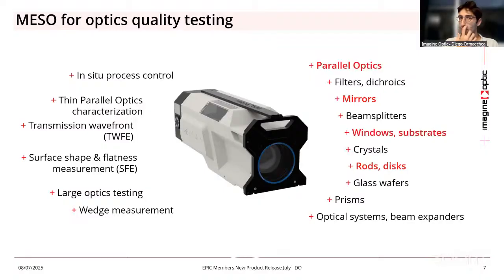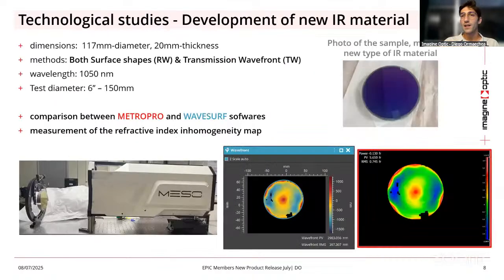So first, an example about how you can measure parallel optics, mirrors, windows, substrates, or disks of any kind of materials by adapting the wavelength. So here it is an R&D team that was studying a new type of infrared material, and they were trying to get the refractive index inhomogeneity map. To do so, we measured both surface flatness and the transmitted wavefront. And by combining the three maps, we can get the refractive index inhomogeneity map. On the top right, you can see the sample. Then bottom left, the setup. And in the middle, it's the wavefront measurement coming from the MESO. We have an export feature in order to get a file compatible with MetroPro software, which is the most common wavefront analysis software. And that's it.